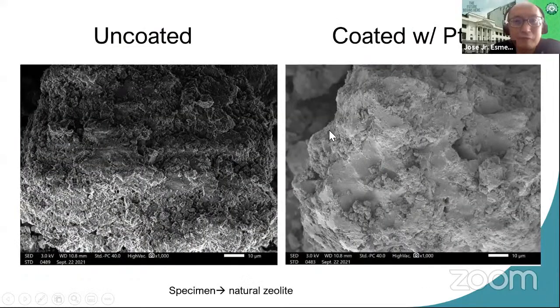So this is an example of an uncoated sample. This is the same raw zeolite from a different sample, uncoated. You can see from here the dark portions as well as the bright contrast. Some are reflected, some are absorbed, so there's an uneven contrast on the surface. Likewise, for a sample coated with platinum, you can see a uniform image with a good brightness and contrast mixture. So that's the big difference.